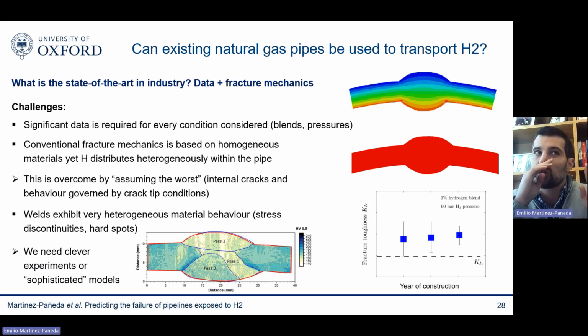The welds. So you have welds that have very heterogeneous material behavior. You have a stress discontinuity, you have hard spots. And you can see this here, right? This is the hardness map provided by EPRI, our colleagues at EPRI. And you can see very significant changes. So you go from areas where you have a hardness of 140 to areas where you have a hardness that is above 240 Vickers hardness. I mean, these are significant differences. You're almost doubling the hardness. And we know that hydrogen susceptibility is very sensitive to hardness.